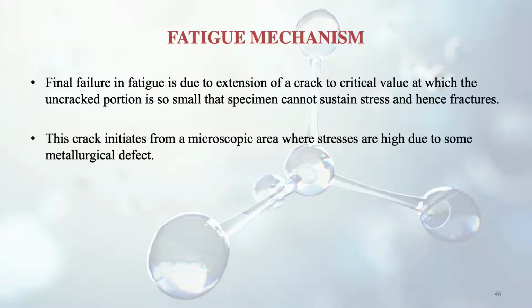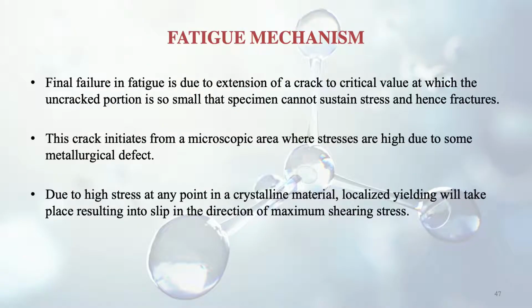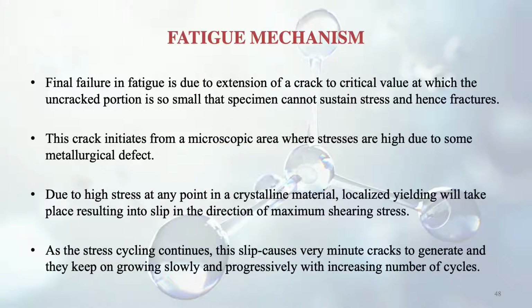This crack initiates from a microscopic area, as I told you, where stresses are high due to some metallurgical defect. So stresses can be high in that region where the crack is, even if the crack is small, due to some metallurgical defect. There are various kinds of metallurgical defect. That's why manufacturing defect and metallurgical defect are important. Due to high stress at any point in a crystalline material, localized yielding would take place, resulting in slip in the direction of maximum shearing stress. So slip happens in this case, and shearing stress is also causing this particular crack to grow. As the stress cycling continues, the slip causes very minute cracks to generate, and they keep on growing slowly and progressively with increasing number of cycles, like I have explained to you earlier.